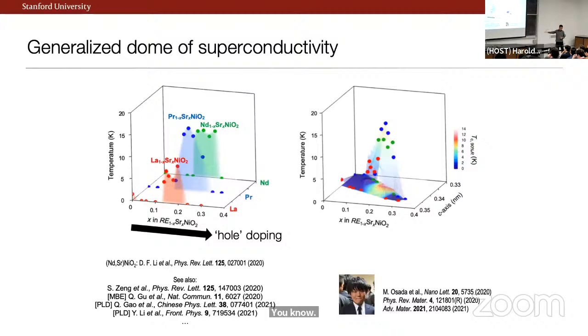So when I showed you that introduction to a large class of unusual superconductors, one of the things I showed you was they're often characterized by a dome of superconductivity, right? So, we spent years wandering in the dark, but once we found something, there's lots to do. And certainly we found with different materials manifestations of this as a function of, this turns out to be a hole doping axis, a generalized dome of superconductivity in this kind of parameter space. I should also hasten to add that around this time, lots of other groups came into this field and doing their own beautiful work using various, again, thin film growth techniques. Okay. So anyway, the message of this slide is that this also at least has that phenomenology that I have a superconducting dome.